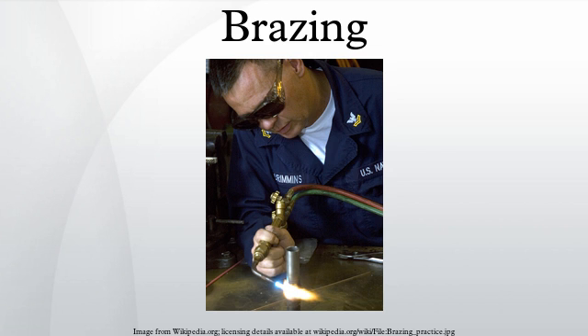Flux can be applied in any number of forms including flux paste, liquid, powder or pre-made brazing pastes that combine flux with filler metal powder. Flux can also be applied using brazing rods with a coating of flux, or a flux core. In either case, the flux flows into the joint when applied to the heated joint and is displaced by the molten filler metal entering the joint.